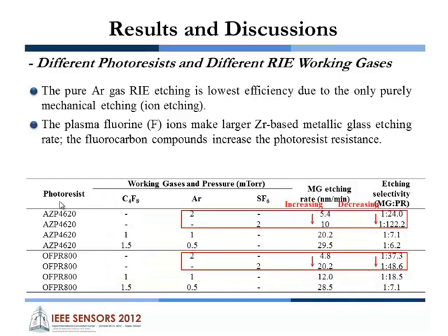And when comparing these two parts, for SF6 the metallic glass etching rate is increased, while for argon it is slow, and the etching selectivity does not increase. Why? Because SF6 has no fluorine carbon compounds, so it cannot increase the photoresist resistance. So from this result, maybe for the working gas we should choose this one, which can etch the metallic glass faster and also increase the photoresist resistance.